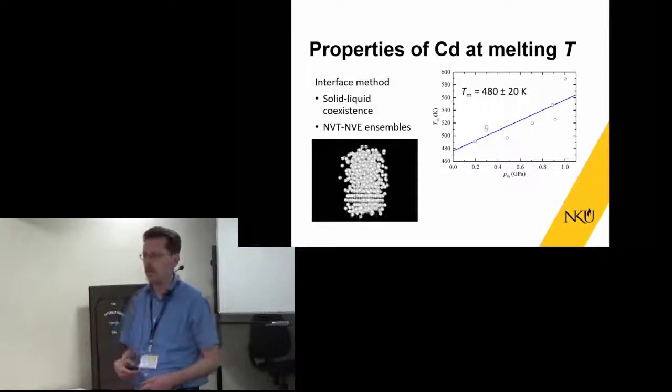I've only run very small simulations as far as numbers of atoms are concerned, so we get a lot of scatter here. But I think this is sufficient to indicate very roughly that the simulation is predicting a melting temperature slightly below 500 kelvin, which is almost 100 degrees kelvin below the experimental point. In fact, the model is underestimating the melting temperature.